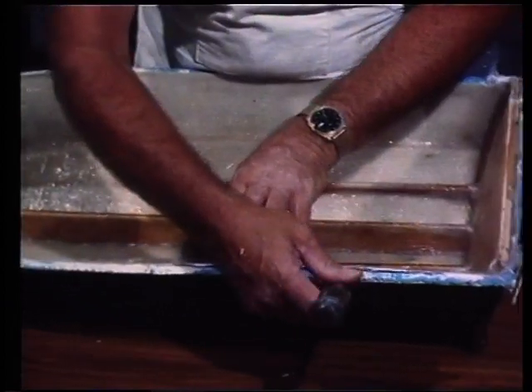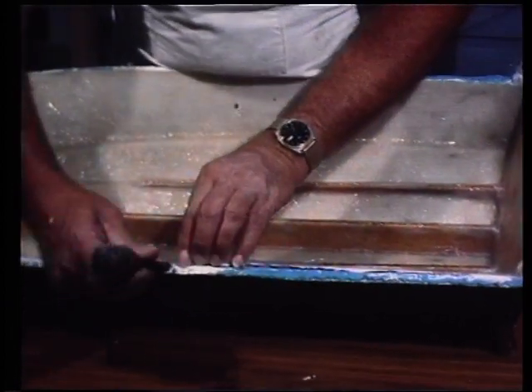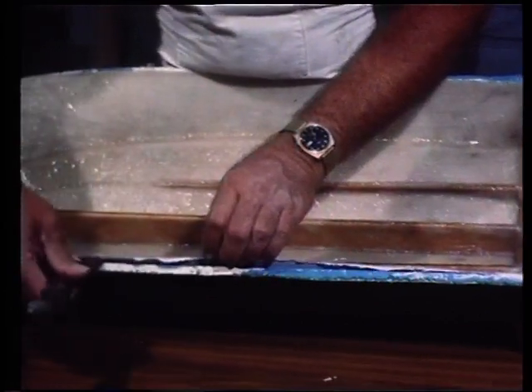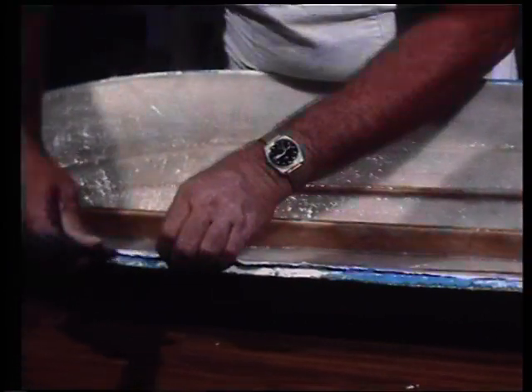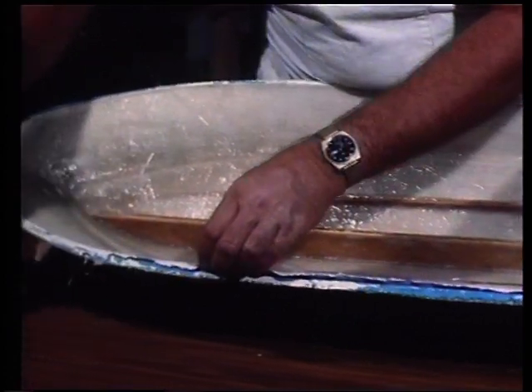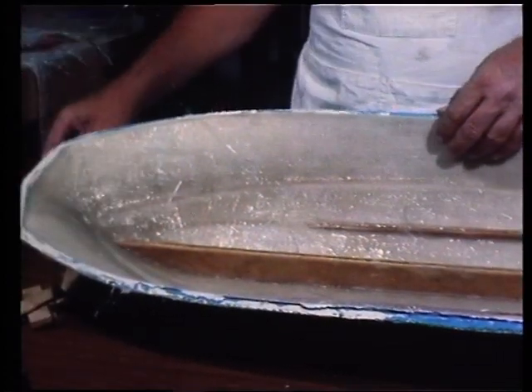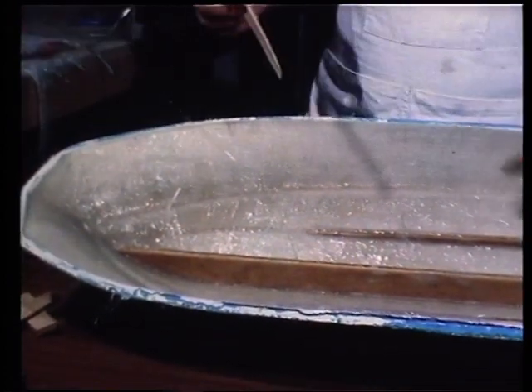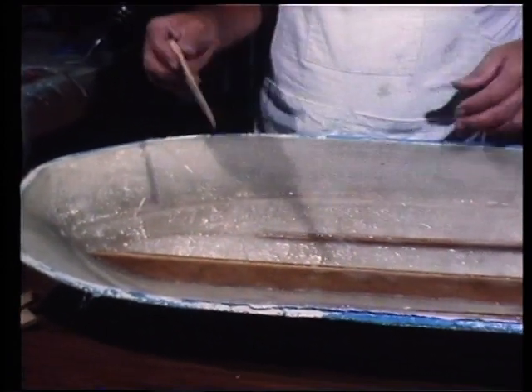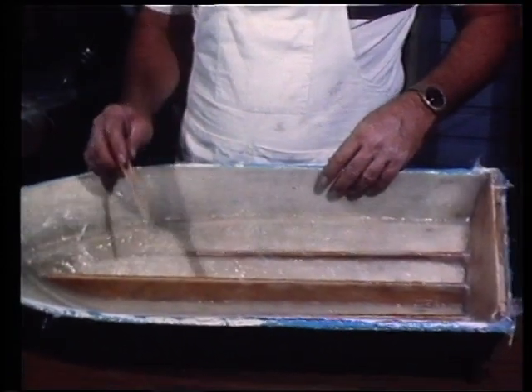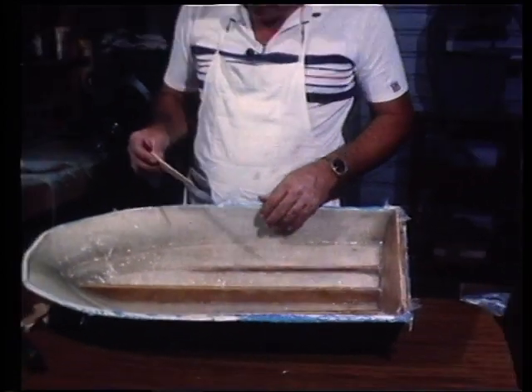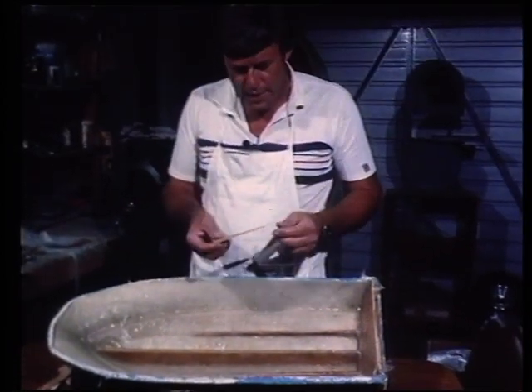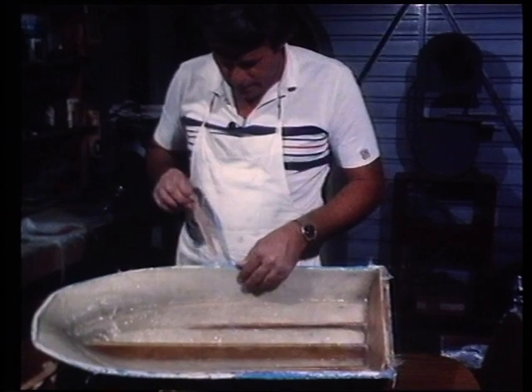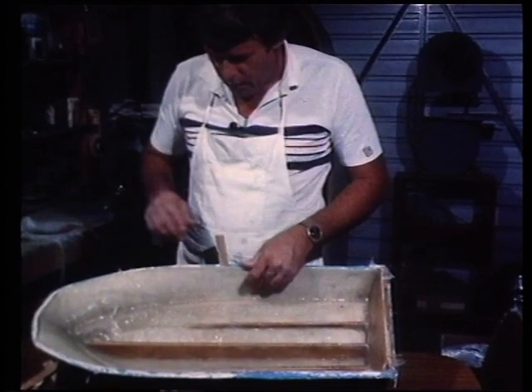Now I'm using a chisel here to pry the top edge of the moulding away from the mould. Obviously you have to be very careful. Now that popped extremely easily. In fact, it's released now. But if it is a little reluctant, and you'll generally find that with a larger moulding, you may have to exert pressure in certain areas, and you do that by making up wedges such as that little wooden one there. Pry the top away and drive the wedges down.